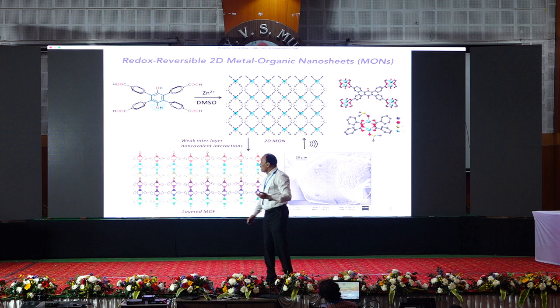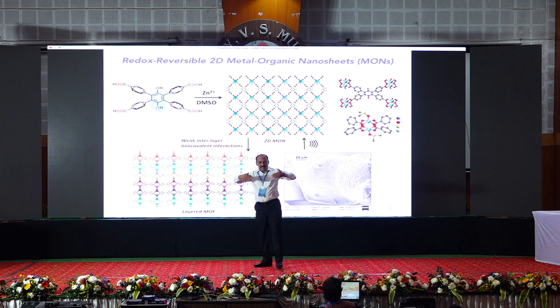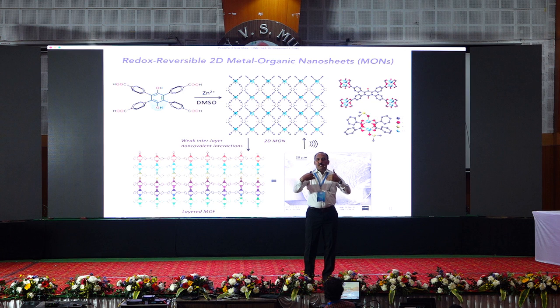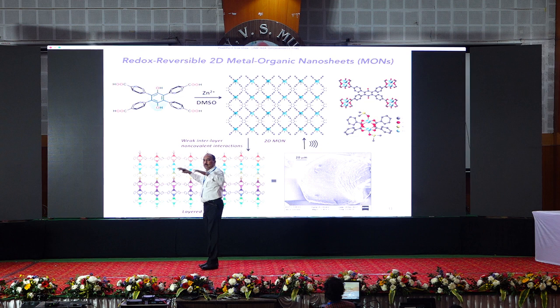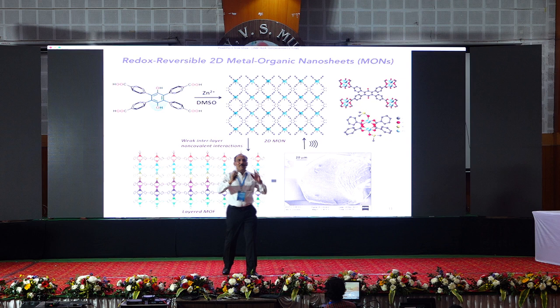Now, I take this dihydroxy tetracarboxylic acid. Now, because the hydroxy groups are at ortho position, very proximately placed, now they cannot be planar, they're twisted. And because they're twisted with respect to the central ring here, now the propagation in the direction perpendicular to the plane is very difficult. Now you do put a metal, the carboxylic acids undergo basically metallation, and you get to